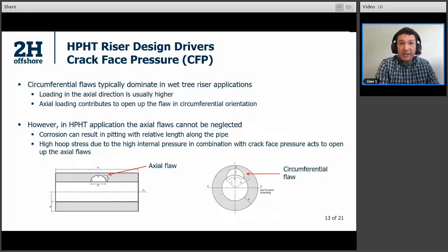In the conventional SCR riser application, loading in the axial direction typically governs the design, and axial loading in the riser opens up the flaw in the weld in the circumferential direction. However, for HPHT conditions, we have high pressure, which means we have a hoop stress. That hoop stress opens up the cracks in the axial direction instead of the circumferential direction. And if you have localized pitting due to corrosion in the axial direction, it is important to consider these effects in your fracture mechanics design, including the crack face pressure.